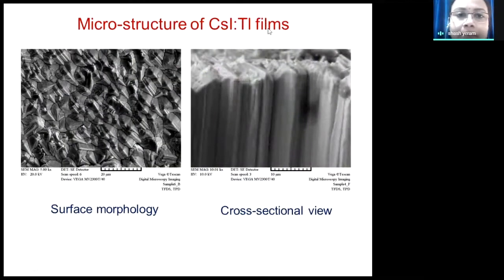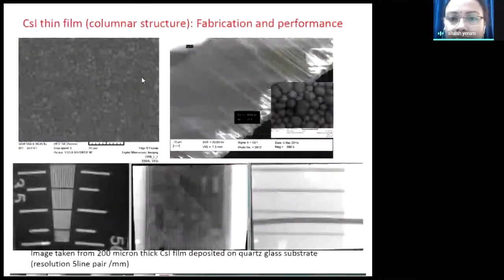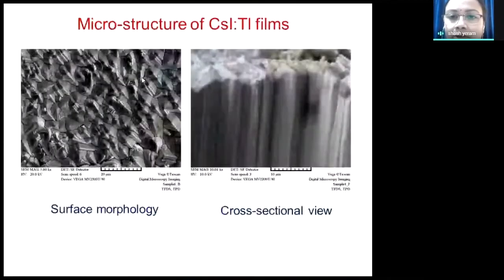So this is the microstructure of the cesium iodide film. Cesium iodide has this very good property that whenever a film is growing, it has a micro columnar kind of structure, meaning there are needle shaped structures. As you see, the diameter of one needle is 10 micrometer to 20 micrometer, and not more than that, and very regular. So this needle shaped structure is a single crystal in itself.